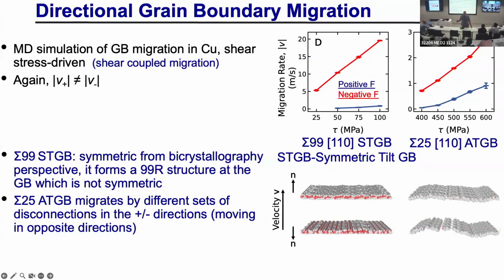So why is that? Well, it turns out, by the way, if it's a symmetric boundary, it doesn't know the difference between up and down. So what's the difference? Well, it turns out that for this particular grain boundary, the boundary transforms to what we call a 99R structure. It's a long story, not really relevant for the talk. But the point is, it'll form a structure, this 99R structure, which is different up and down. But if I look over here, it'll pick at random the structure, say, pointing up. And way over here, it'll move with the structure pointing down. So if I average over a very large boundary, it's equally likely to go up and down. So overall, the mobility is the same in both directions. So this is a very special case. So even when you have a symmetric boundary, locally, it could be asymmetric, but macroscopically, it still has to be same velocities in both directions.